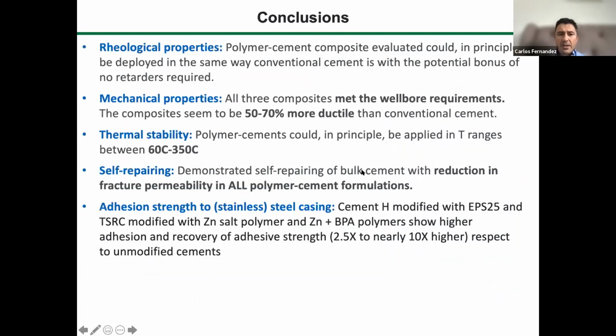So in conclusion, in terms of rheological properties, a couple of the polymers that we use act not only as a material that can bring about self-healing behavior to the cement, but also can act as a retarder. So you can reduce the cost of the cement by removing the retarders just because you are using the polymers.